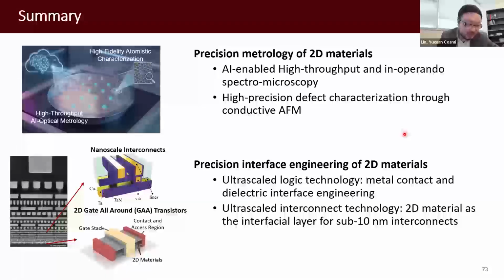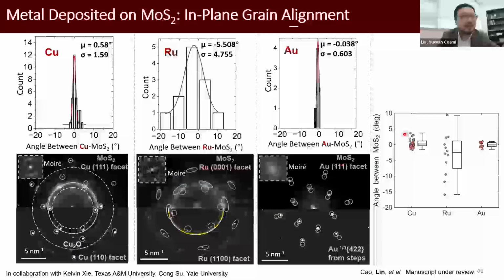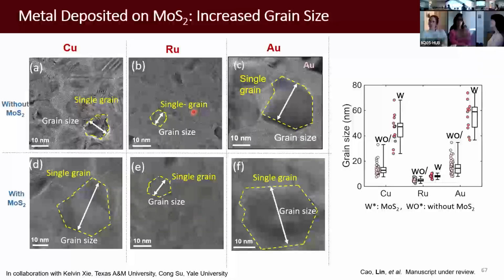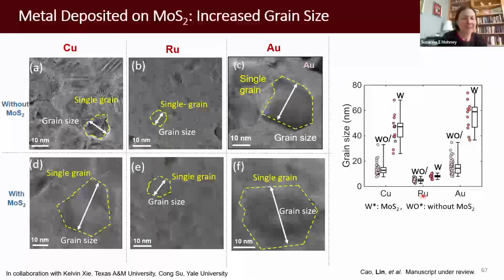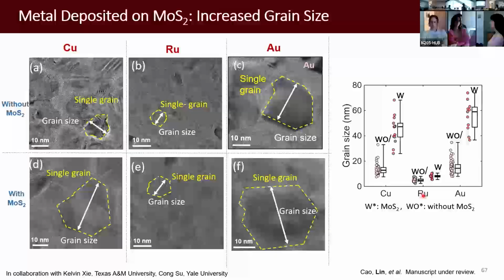Yeah, so what we are trying to use is the planar deposition approach, e-beam evaporation. We deposit on 2D materials at room temperature. If the sample is super clean, we can observe that template effect. For the Damascene process, it has two components. The first one is the seed layer, and sputtering is more challenging to deal with. Actually, the ruthenium one in our study was done by sputtering. That's also why the results are not as good as the other one. We create a lot of defects on the 2D material. But there is still some room to optimize that, compared to evaporating. Once we have that templated seeding, then for the electroplating, I still need to learn.